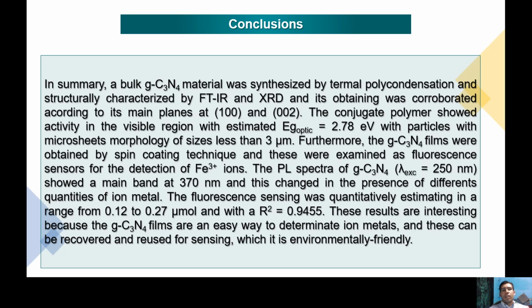As conclusion, we made the C3N4 by thermal polycondensation, and we made the characterization by infrared and X-ray diffraction, and we corroborate its main planes and its main functional groups. And also we can find this conjugated polymer presents activity in the visible region, and also we can find particles with microsheet morphology. And also with this material we made C3N4 films by spin coating technique, and we use these films in order to determine quantities of the iron metal ion.